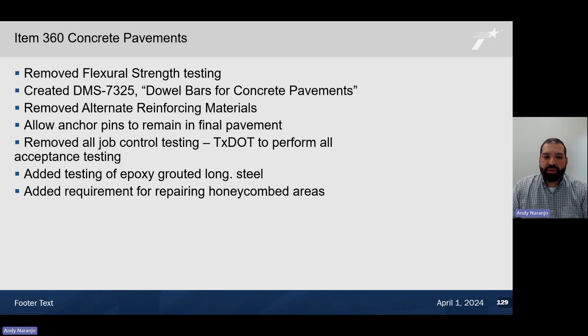We also added a requirement for repairing honeycomb areas. This generally happens in formed pavement where the consolidation with the vibrators did not get close enough to the forms, leaving honeycomb areas. These areas upon form removal will have to be chipped out and investigated down to sound concrete, and either repaired or placed with the adjacent lane pavements.